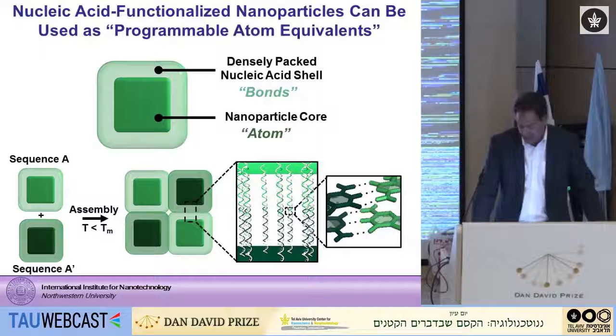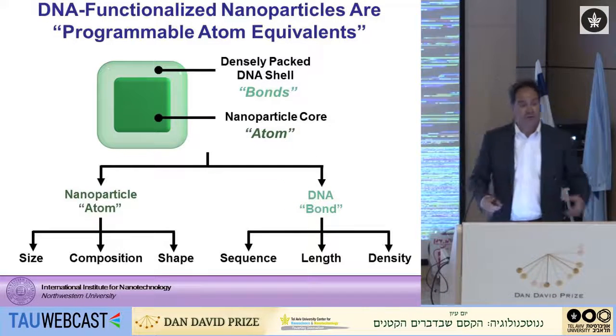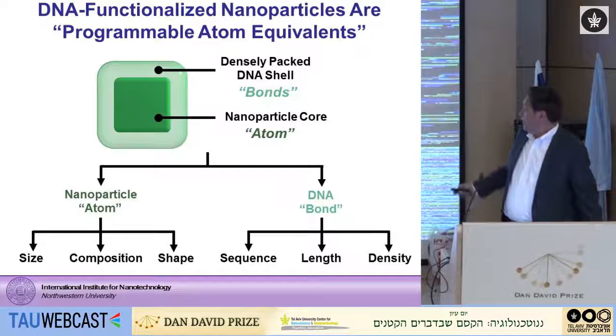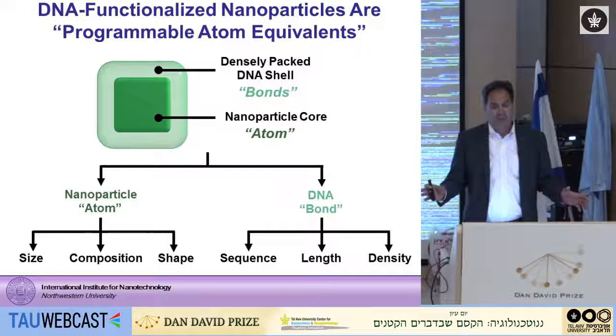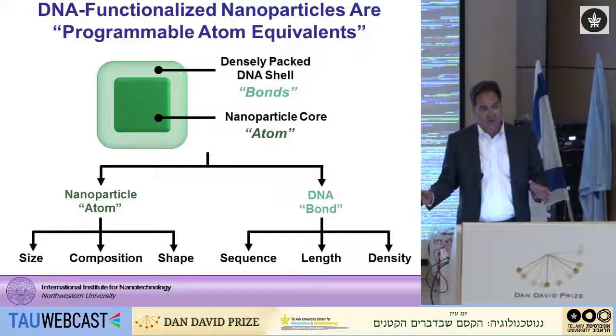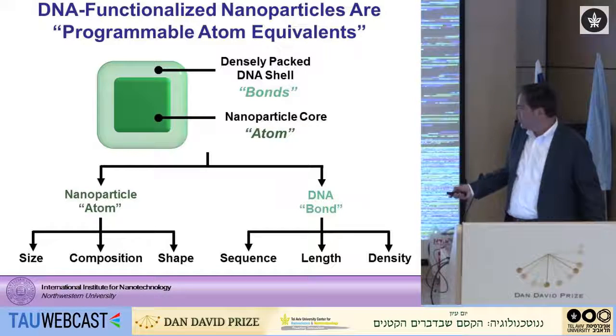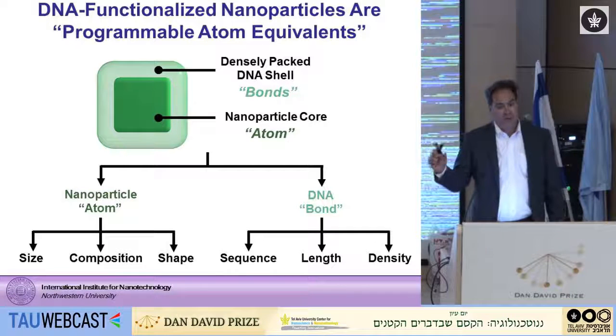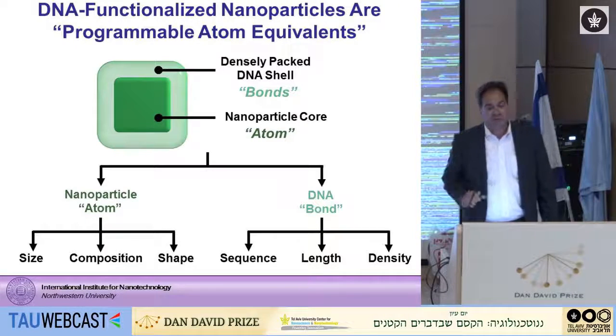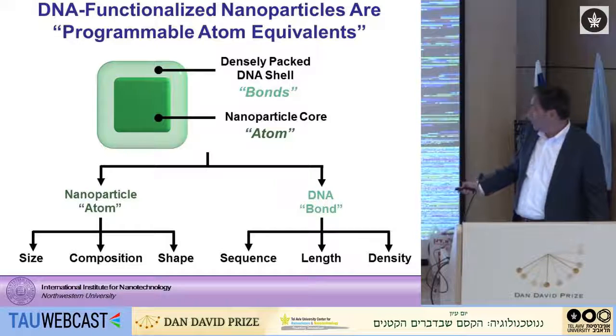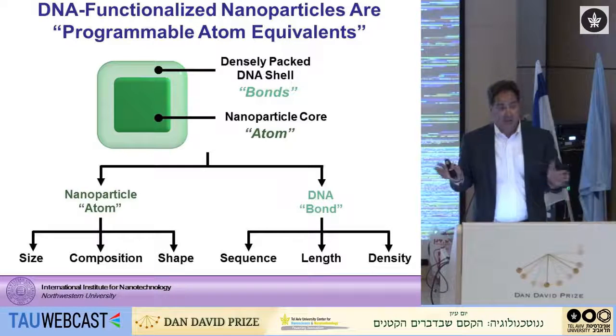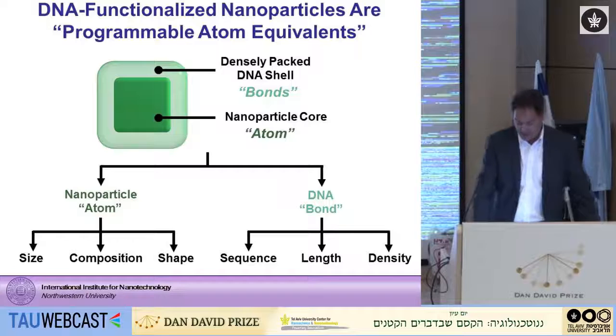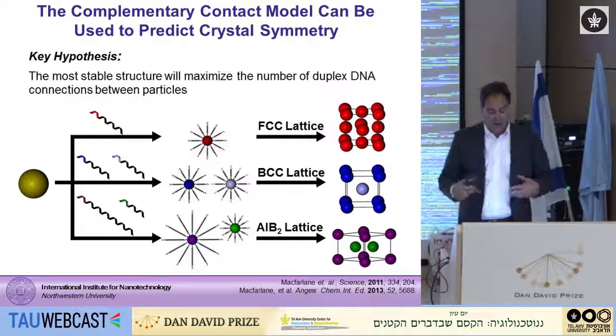And any high school student can tell you the different sequences that are important in terms of recognizing others, right? ATGC. If you think about this, and I want you to think about it because it's really a new type of chemistry that is similar to some of the things that we do, but very different in other regards. This is interesting because we can independently control the bond from the atom. And you can't do that with conventional chemistry. We're stuck with what nature gives us with the elements that we have in the periodic table. So with the particle, I can independently control size, composition, and shape. And with a bond, I can control sequence, length, and density, the number of interaction pairs that can take place, for example.